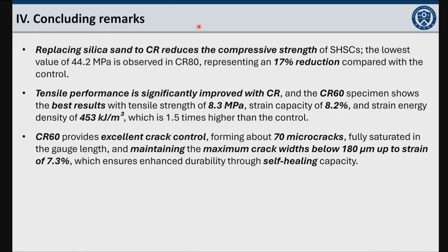The CR60 mixture provides excellent crack control, forming about 70 microcracks, fully saturated in the gauge length, and maintaining the maximum crack width below 180 micrometers up to a strain of 7.3%, which ensures enhanced durability, especially through its self-healing capacity.